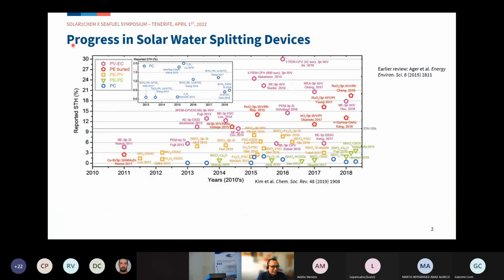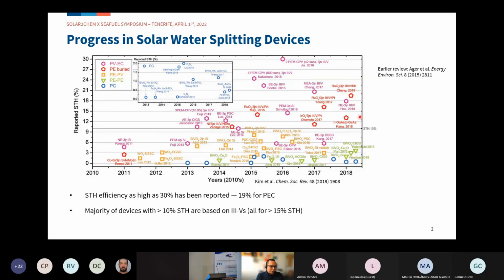So I begin with this little introduction on the current state of the art on solar water splitting devices. Adelio presented a similar plot. This one was taken from a relatively recent paper that looks at the devices within the last decade or so. And from this plot, we can learn a couple of things. First of all, solar to hydrogen efficiency as high as 30% has actually been reported with the combinations of the PV and electrolyzer. And if you consider the integrated PEC, we have also pretty high solar to hydrogen efficiency of very close to 20%.